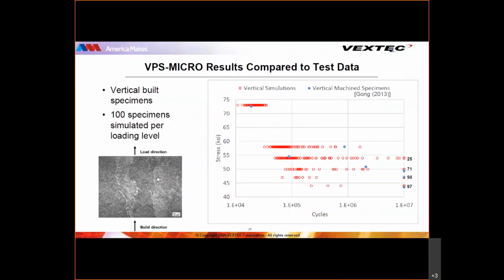Yes, as we drop in stress there, and this is a good example. But you do notice that in this particular case, as you get towards 50 KSI, you've got 71 runouts. So you still have a large percentage that run out, but you might notice that there were also some failures at say 1 times 10 to the 5th, whereas the one part that was tested failed at say 2 times 10 to the 6th. So indeed, even in the model, mechanistically, what's going on at 70 KSI will be different than what's going on at